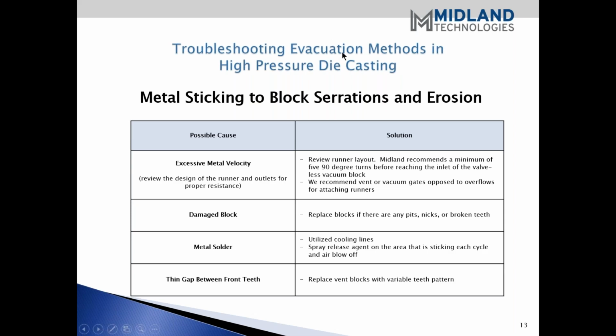Okay. The next issue is metal sticking to blocks, serrations, and erosion. Again, the possible cause, we hit it right away: excessive metal velocity. And again, we're still emphasizing the runner layout and putting the 90-degree turns in there. We recommend vent or vacuum gates as opposed to overflows for attaching runners. Then you also have the possible cause of a damaged block. Of course, you want to replace blocks if there are any pits, nicks, or broken teeth.